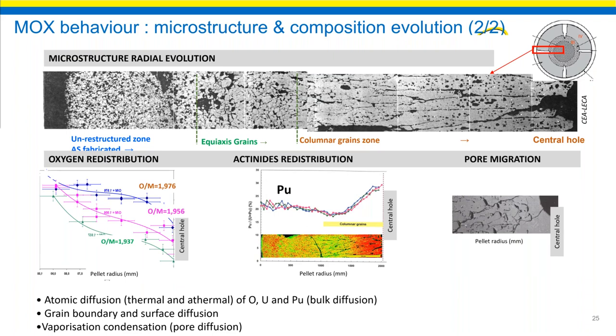The thermal gradient is even higher than 5,000 Kelvin per centimeter. And because also of the high temperature, higher than 2,000 Kelvin, we will form a central hole early in the irradiation. In fact, the initial porosity resulting from the fuel pellet fabrication is homogeneously distributed in the pellet as small pores. But due to the very high thermal level, these pores are redistributed along the radius through an evaporation condensation mechanism between the hot side and the cold side of each pore, as you can see on the graph on the right side. So this matter movement contributes to the central hole formation and the columnar grain structure.